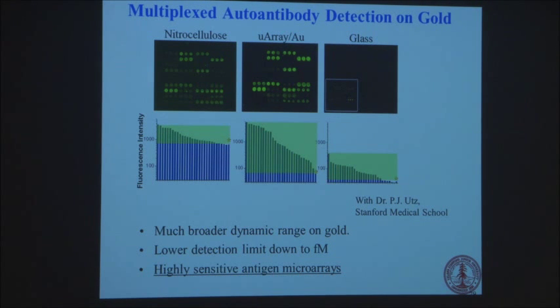And then there are other kinds of substrates, like nitrocellulose paper, which has a lot of pores, so you can get a lot of things captured, but at the same time you also have very high background. So your dynamic range is very limited in both cases, but on the gold substrate, you really boost the signal and minimize the non-specific signal. So I think this is a technique that can really allow the array to detect molecules at very low concentrations, which I think will be relevant for diagnostics.